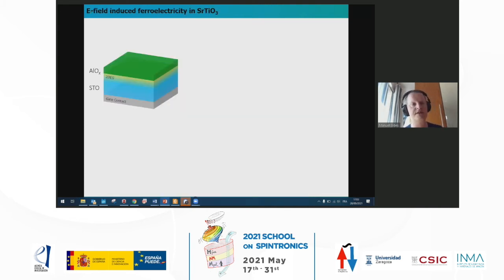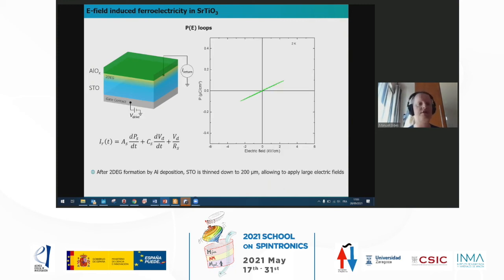And so we demonstrated this effect with the same 2DEG, STO aluminum oxide 2DEG, but there we induce ferroelectricity in STO by applying a very large electric field. STO, as you may know as well, is very close to being ferroelectric. If you replace 0.5% of the strontium ions in strontium titanate by calcium, STO becomes ferroelectric. Also, just a little bit of strain is enough to make it ferroelectric. And there are a few papers in the literature going back to 1956 which show that if you apply a large electric field in STO, you stabilize a ferroelectric state. This is not fully understood, but this was observed by many groups.